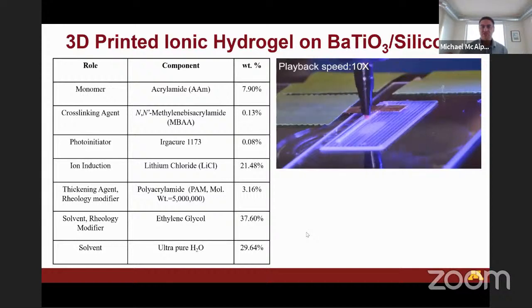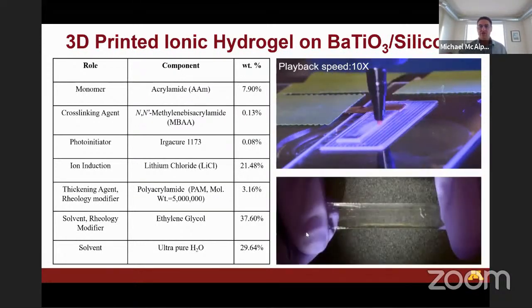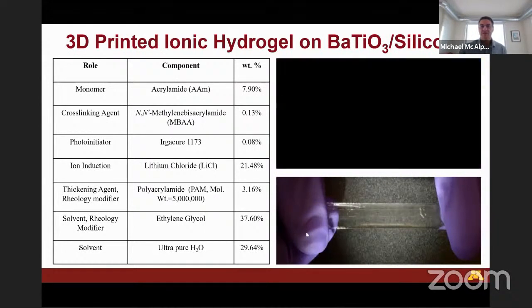So, same type of sandwich structure that Ziguang showed, but now fully 3D printed: ionic hydrogel, silicone with barium titanate, and then another layer of ionic hydrogel on the top to create one of these ionic hydrogel capacitors, but used as a sensor or as an actuator. And you can see, of course, it becomes somewhat opaque with the barium titanate, but it is actually still flexible and stretchable, and it's under UV the entire time in that video.